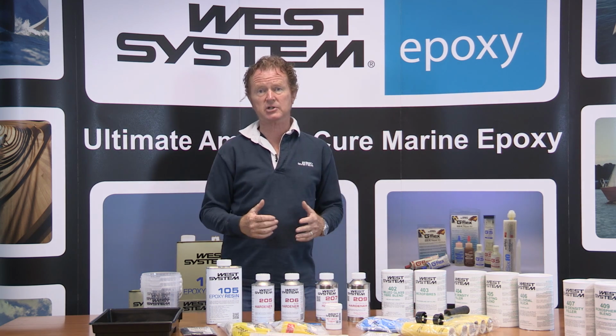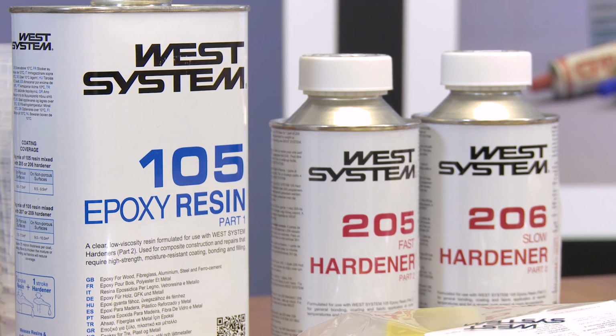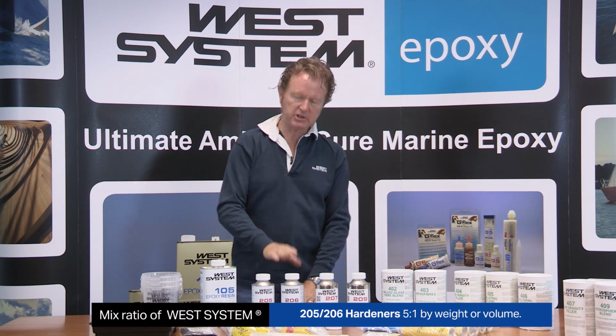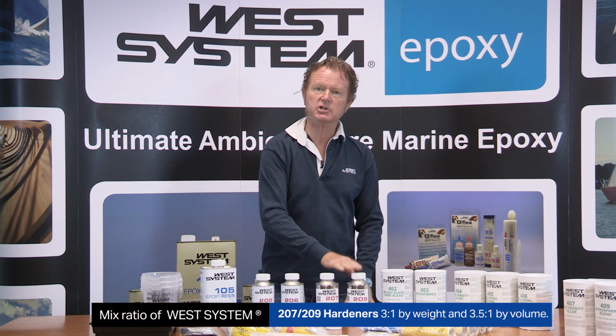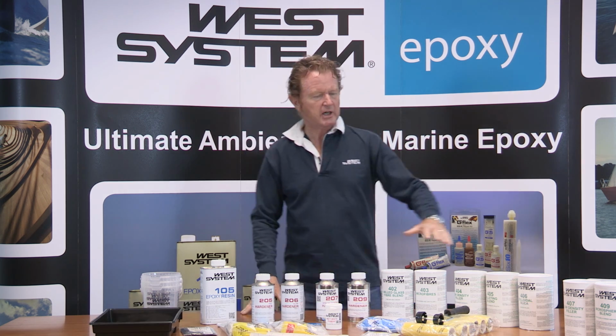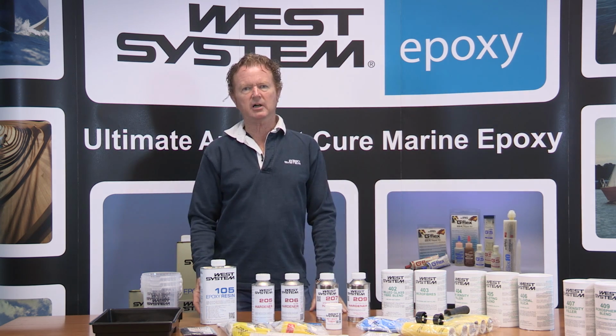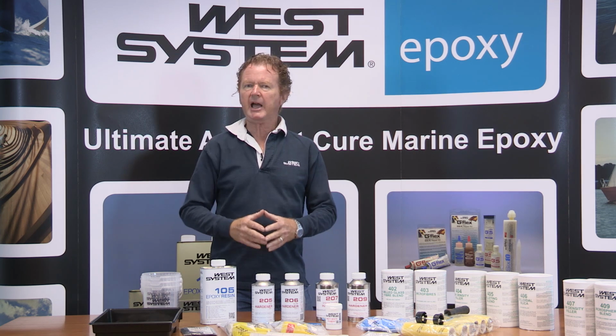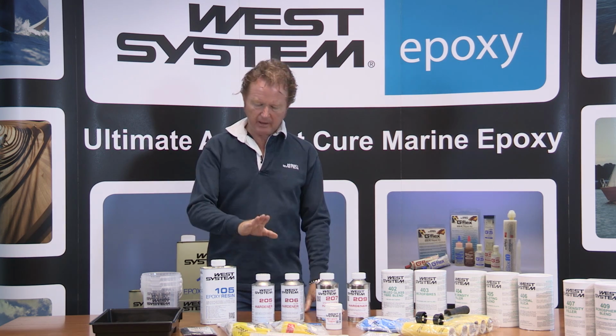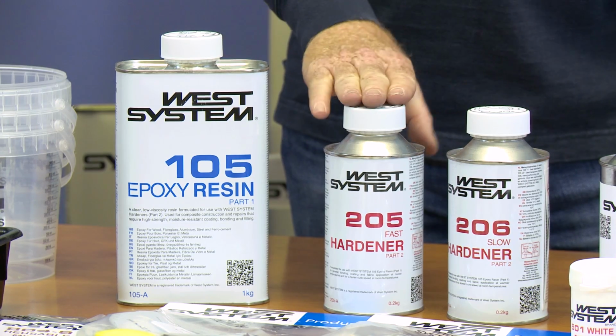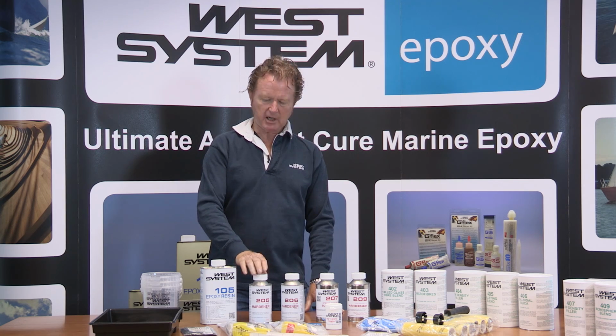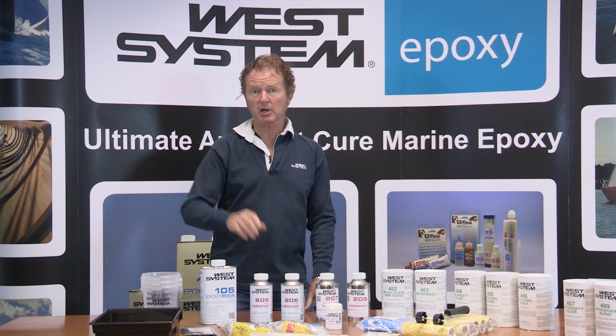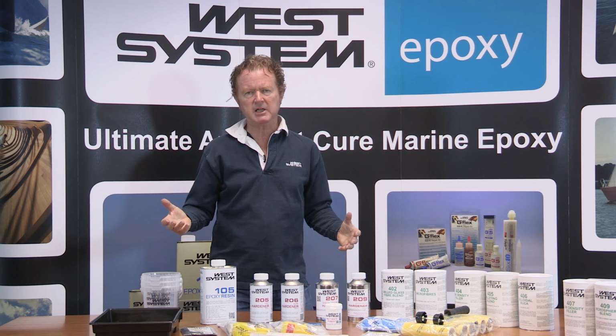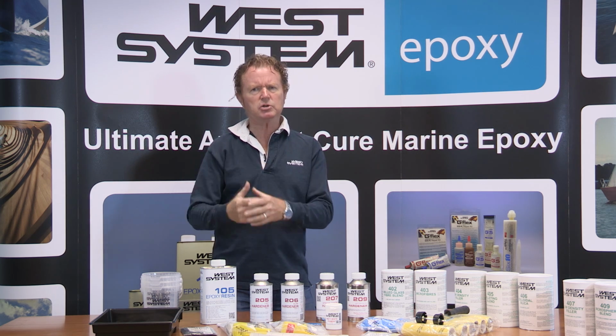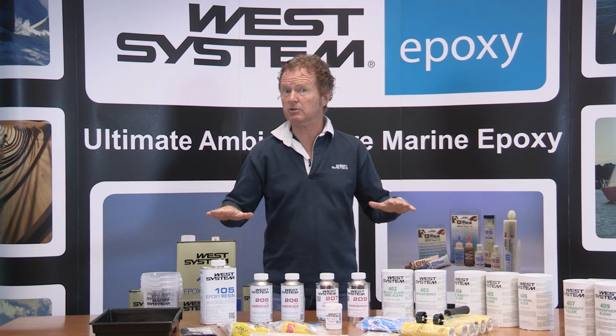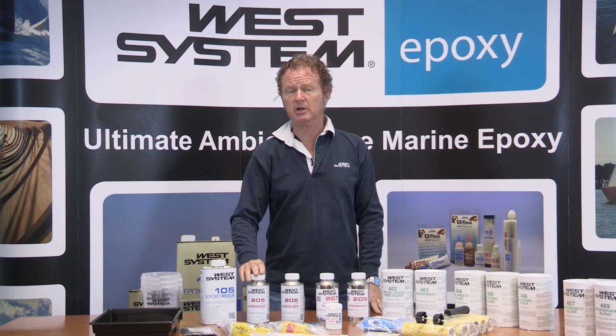many different tasks. We have our 105 resin, and we have our 205, our 206, our 207, and our 209 hardeners. We have our range of fillers. Now, quite where do you start? If you have a small job and you're based in the UK or Northern Europe, then we sell mainly our 205 hardener. This gives you a good working time. It gives you a good pot life of 10 to 15 minutes and gives you good quality working time right down to 5°C. So it's very, very versatile.